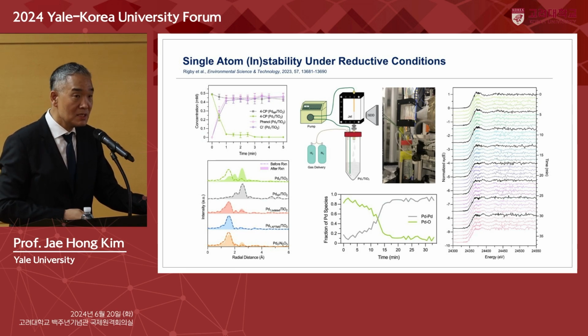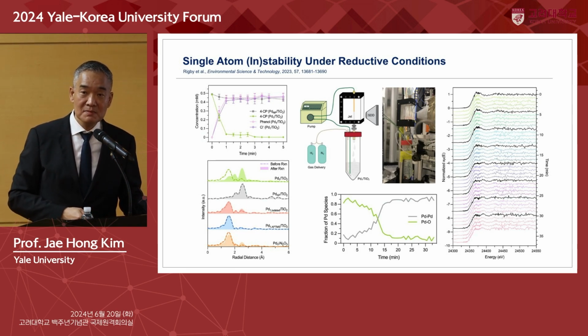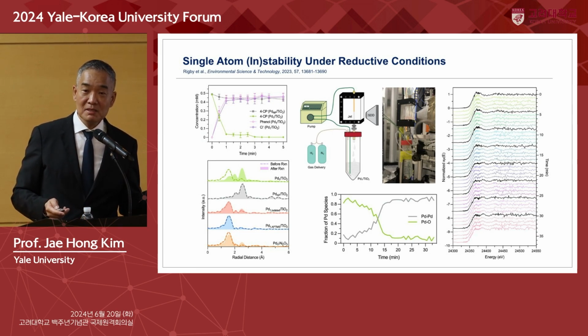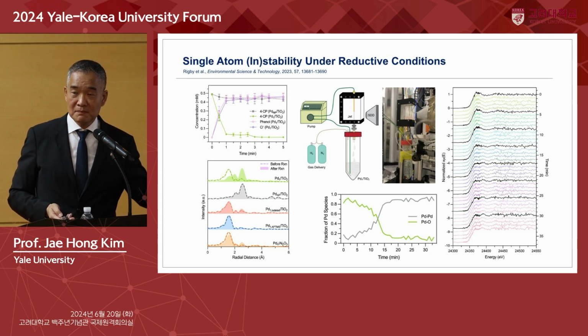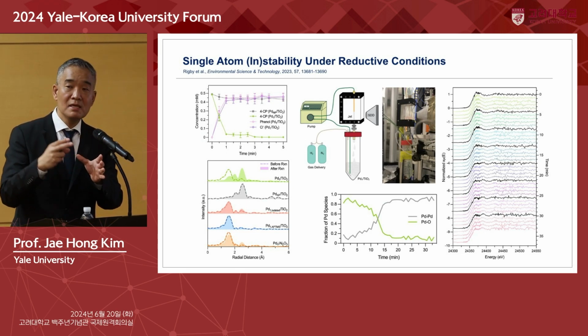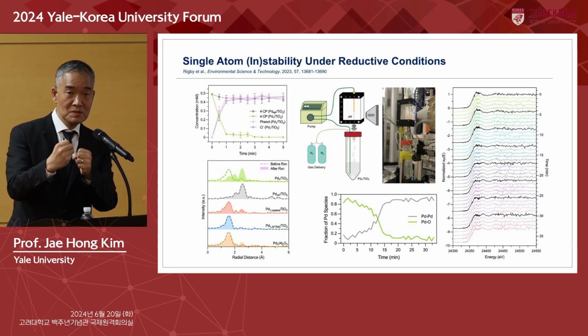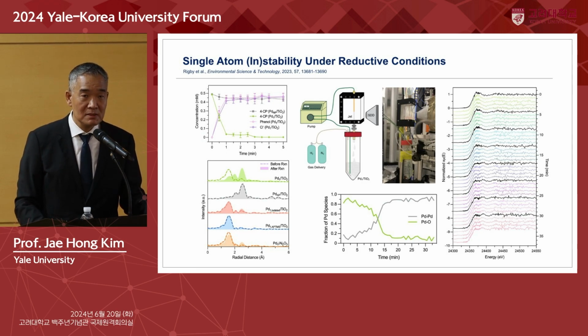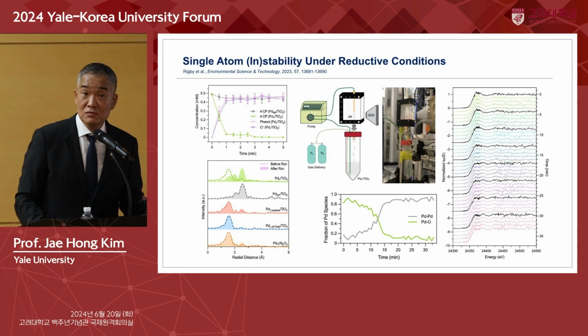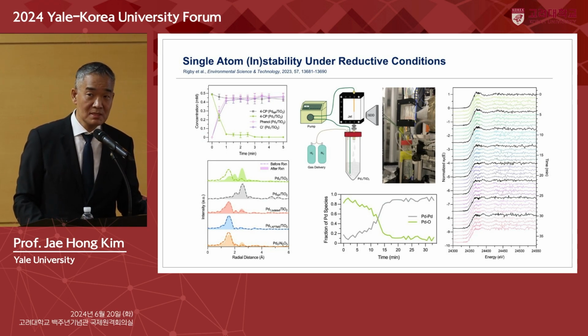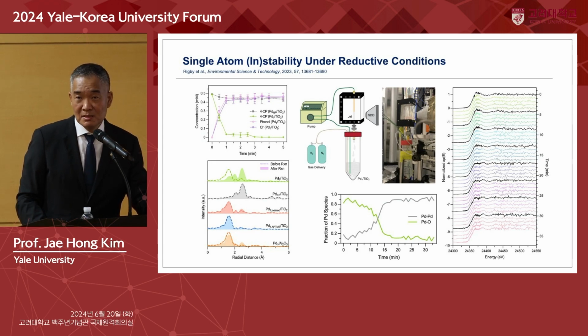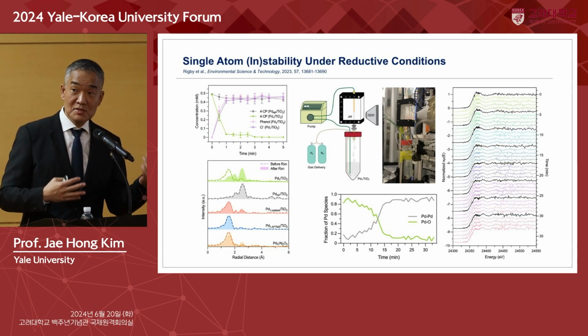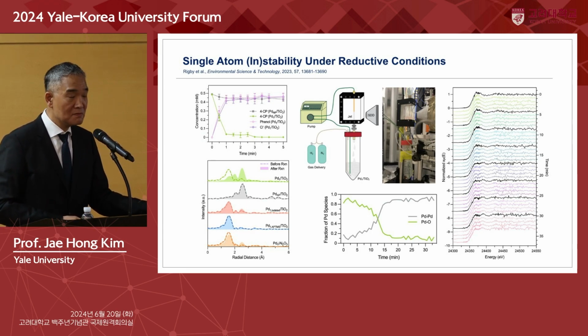In a pretty recent publication, we are looking at, again, 4-chlorophenol degradation using single atom catalysts. It works well with a single atom catalyst, but we found that they actually change over time. We use a lot of X-ray from synchrotron sources at Brookhaven. We did an in situ cell, and we are looking at how the single atoms change over time as they react in the aqueous phase. We do find that they migrate, but not always. We still do not know the answer. For some of the transition metals, like copper, they migrate pretty readily, but iron is more firm, depending on the substrate. And depending on the target reaction, their reactivity seems to change. So we don't have a clear universal explanation of this, and we are at the stage of just looking into diverse scenarios.